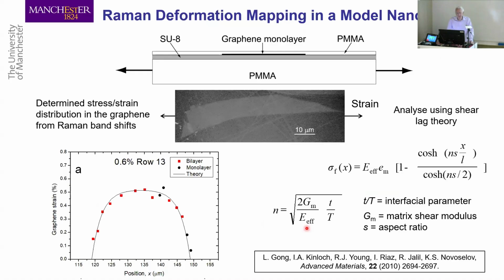Now we want to see the behavior in a composite. So we then decided to make a model composite, again with Professor Novoselov. He produced a composite like this, where we had a polymer beam with a graphene monolayer, 1 atom thick, sitting there, sandwiched between 2 polymers. We then deformed it, and then did measurements along the length of the graphene. And we measured the strain in the graphene using our calibration in the previous slide against position. And we found our data points are there. And we found we got this sort of behavior on this curve.